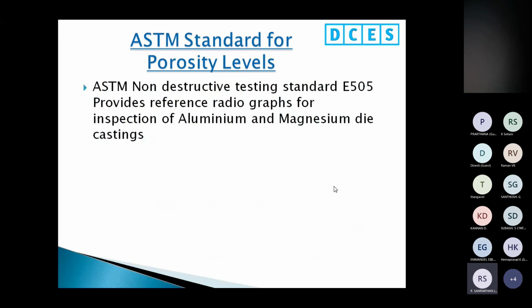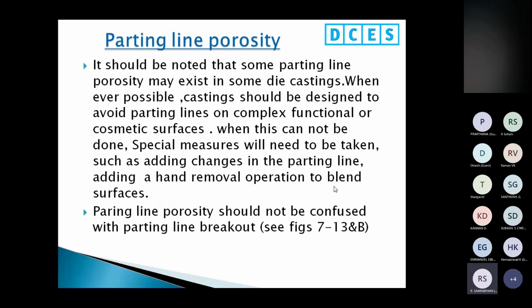ASTM standard for porosity level. The ASTM non-destructive testing standard E505 provides reference radiographs for inspection of aluminium and magnesium die castings. This can be used for reference. Parting line porosity: it should be noted that some parting line porosity may exist in some die castings. Whenever possible, castings should be designed to avoid parting lines on complex functional or cosmetic surfaces. When this cannot be done, special measures will need to be taken, such as adding changes in the parting line, or adding a hand removal operation after the casting to blend the surface.